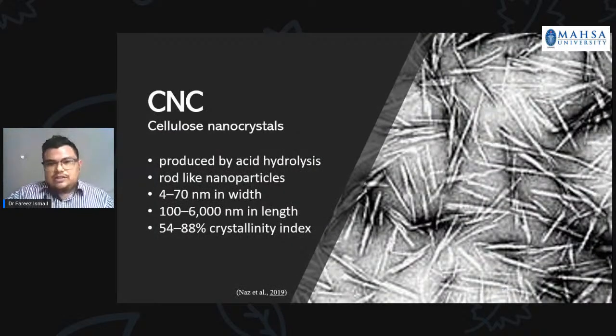So next, I will just focus on the nanofibers, of which firstly we have cellulose nanocrystal. It is produced by acid hydrolysis. It consists of cylindrical, elongated, less flexible, nanoparticle-like structures with 4 to 70 nanometer in width and 100 to 6,000 nanometer in length, and it has 54 to 88% crystallinity index. It actually received a number of names before it was standardized as cellulose nanocrystal. Before this, we called it nanocrystalline cellulose, rod-like cellulose crystal, nanowires, nanorods, sometimes nanoballs. And recently there's confusion with cellulose nanowhiskers, CNW, or cellulose whiskers. We should stick with one, which I think describes the same thing: cellulose nanocrystal.